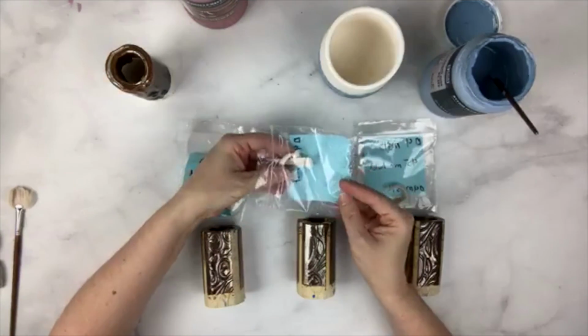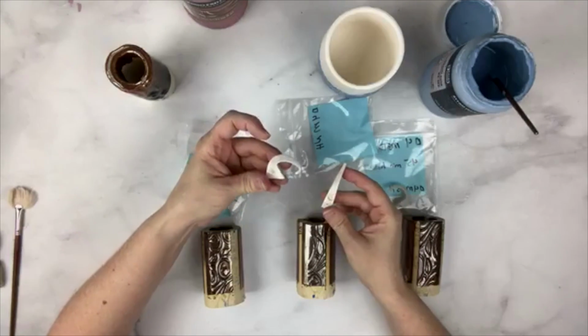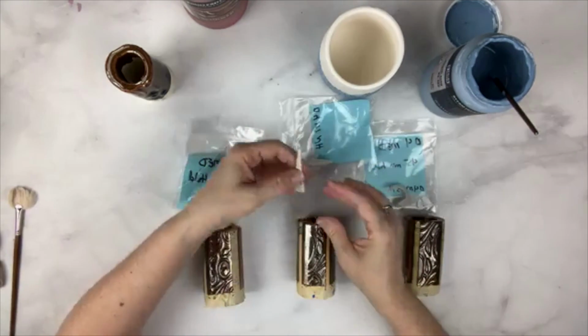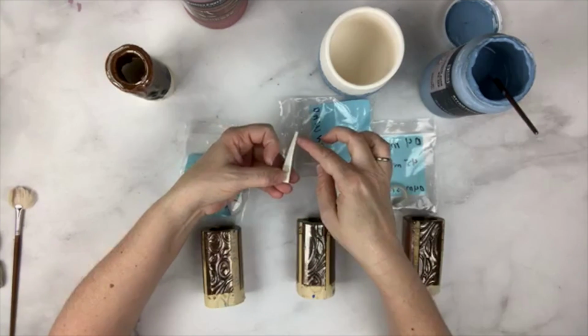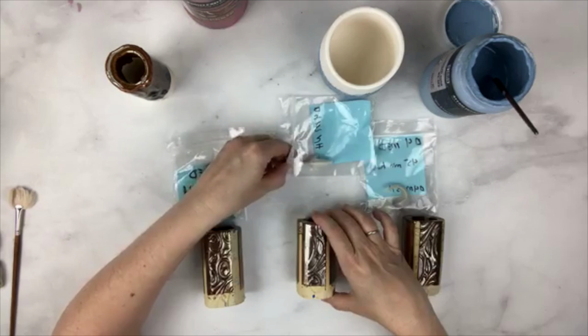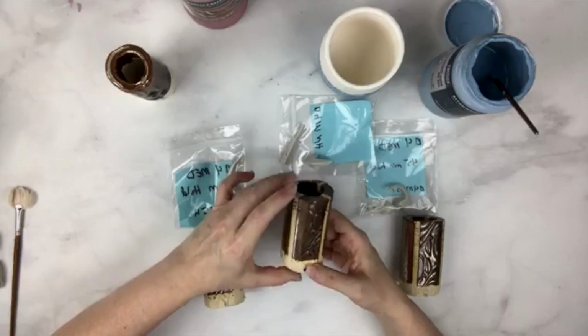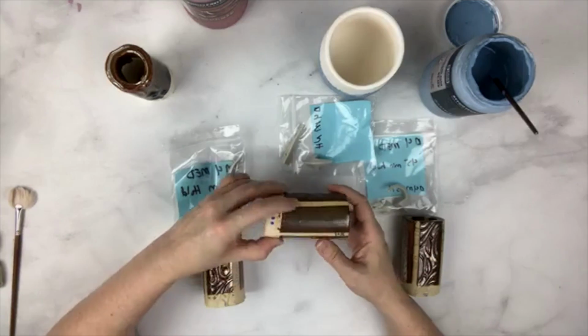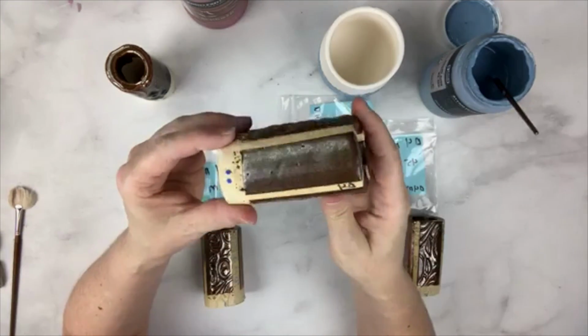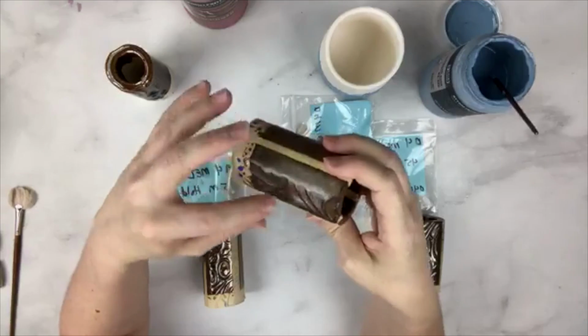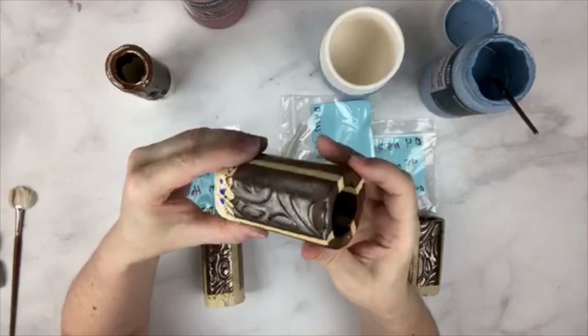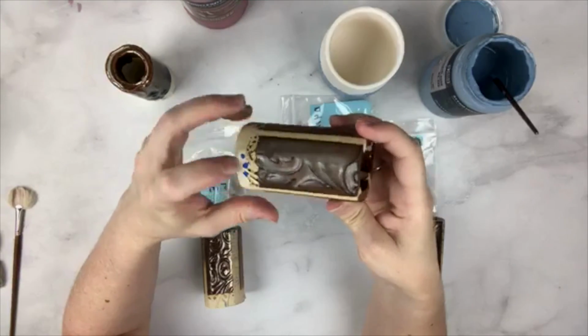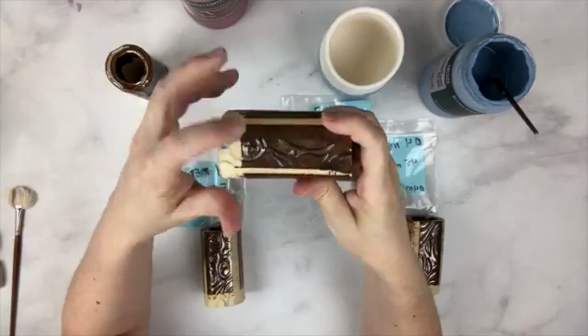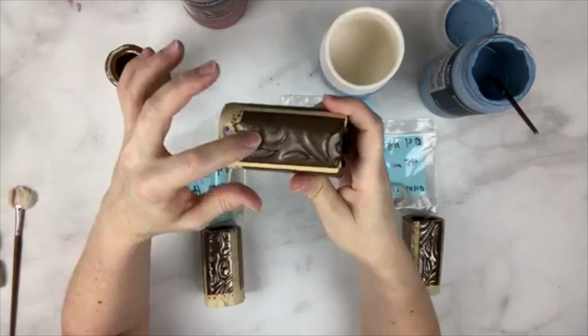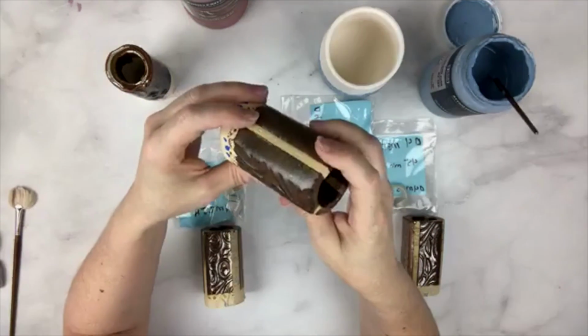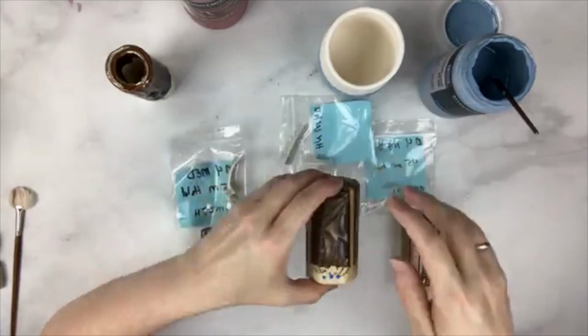For those of you who don't use cones, this is a cone 4, slightly over a cone 4. This is a cone 5. You can see that it's showing the tiniest amount of bend, so it clearly is not reaching cone 5 at all. And you can see that it has a little bit of luster to it, but it does not have that beautiful patina, and it's a little bit dull. This would be 3 coats, and so that is 2 coats, 1 coat, 4 coats. So this is our preferred coat, but you'll notice it's kind of dull. It's not really there yet.